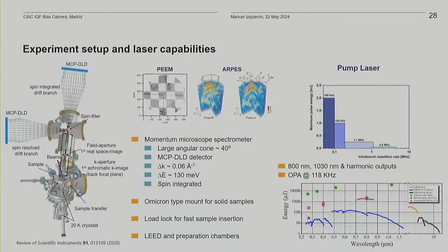What is important to know is that we are using the so-called momentum microscope. Momentum microscopes are very complicated machines, but they are also very powerful because you can do both beam experiments and experiments with angular resolution. You can even put a spin branch to do also spin-resolved experiments. The device that we have has a large angular cone of around 40 degrees. We have an MCP-DLD detector to do time-resolved measurements, an energy resolution around 130 millielectron volts. It's spin integrated, and you can mount standard Omicron samples.